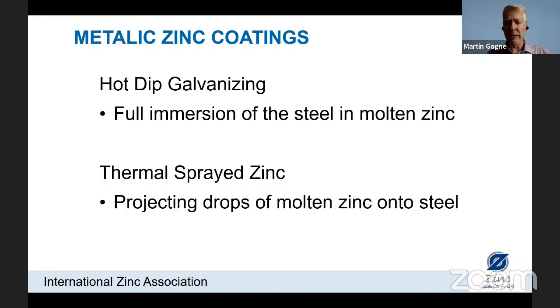And we can coat some larger structures with this process using a technique called double dipping or progressive dipping. We put one end in the kettle and then we flip it over and put the other end in, and it gives us some leeway to do larger structures. But there is a physical limitation because the bath contains the molten zinc.